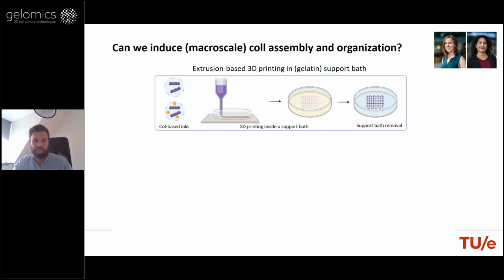The next step, from the top-down approach, was to combine this principle of macromolecular crowding with a process. In this case, we picked extrusion-based printing. The reason for that is that we believe that by shearing the material through the nozzle, we can further confine and promote the assembly and entanglement of the protein molecules. We didn't want to explore any chemical modifications to our collagen, because we believe that will have a harmful impact later on. So we just took collagen in acidic conditions.